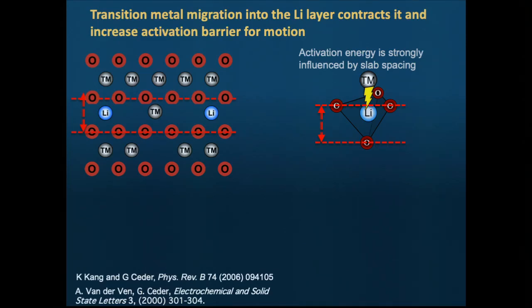If you ever stare at it carefully, on every face of an octahedron is a tetrahedron. And this is the activated state. When lithium is in the activated state, it's very close to the transition metal. So this electrostatic repulsion controls the activation energy for lithium diffusion. Now you can see if the spacing here is large, then these ions can stay far away from each other, and you have good lithium mobility. If you condense the structure by making these planes come together, you increase the activation energy for lithium, and you have no motion anymore. So you cannot charge and discharge your battery at a reasonable rate.